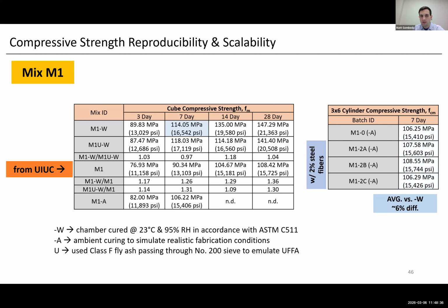Now, if we take it a step further, if we look at the ambient conditions, the first one, the 6%, is the one that was done in the chamber for the smaller scale, and then ambient conditions at the larger scale. But if we compare the apples to apples with both being done in ambient conditions, we see less than 1% difference on average. So we were really satisfied with how we were able to get the compressive strength values to reproduce at the larger batch size.